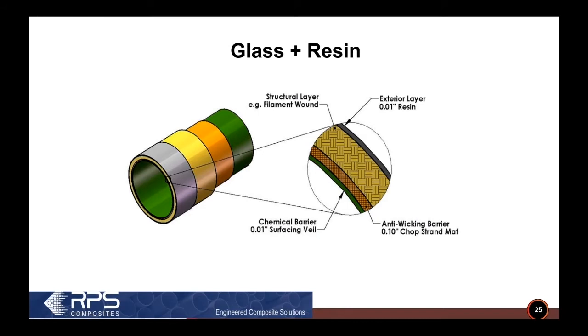So what we do to make a laminate, and this would apply to tanks or piping, is we first apply a resin-rich area to the process side, and we actually use something called a surfacing veil. It's sort of like the chopped strand mat, but much thinner. It comes in a polyester version or a glass version. There are certain times when you'd use one or the other. What you get is about 90% resin, so we don't have a 100% pure resin barrier that might be susceptible to thermal shock. We have about 10% reinforcement, so a little bit of reinforcement, but a lot of resin to give you corrosion resistance.